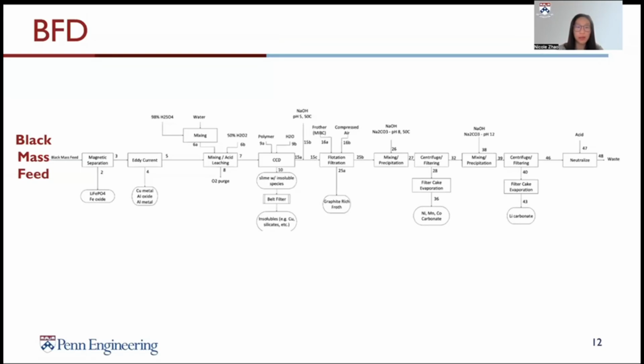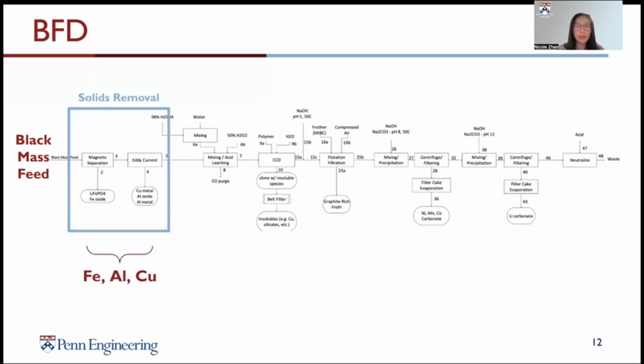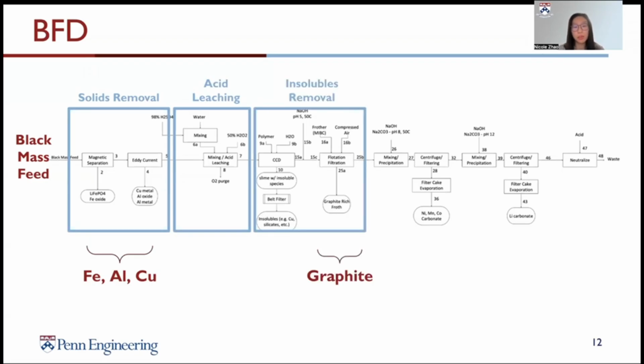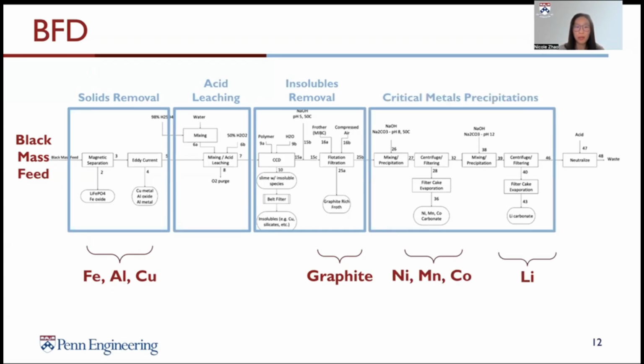Here's the block flow diagram of our proposed process, which is divided up into distinct stages where we extract out our valuable products. The first stage is the solids removal stage, where we extract out iron, copper, and aluminum, followed by an acid leaching step that solubilizes the remaining stream and turns our critical metals into their ionic form. The remaining insoluble material coming out of acid leaching goes into the next step, where graphite, silicates, and remaining copper and aluminum are removed. Finally, critical metals are precipitated out in this final stage where we extract our carbonates of nickel, manganese, cobalt, and lithium.